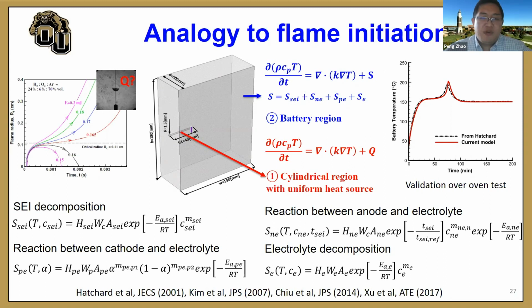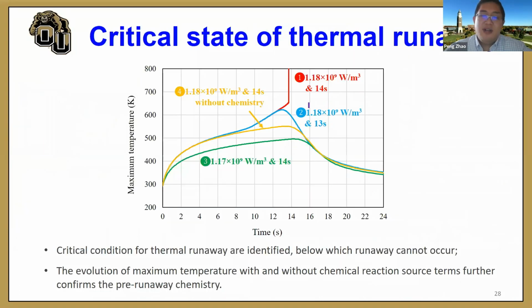And outside of this cylindrical region, we consider the battery. Inside the battery, there can be the potential of these 4 different energy source terms. And we found that there indeed exhibits a critical state. For example, starting from this heat source intensity and duration time, if we reduce the heat source intensity from 1.18 to 1.17, the thermal runaway cannot occur. Or we reduce the duration time from 14 seconds to 13 seconds, the thermal runaway cannot occur. That means this is a critical state.